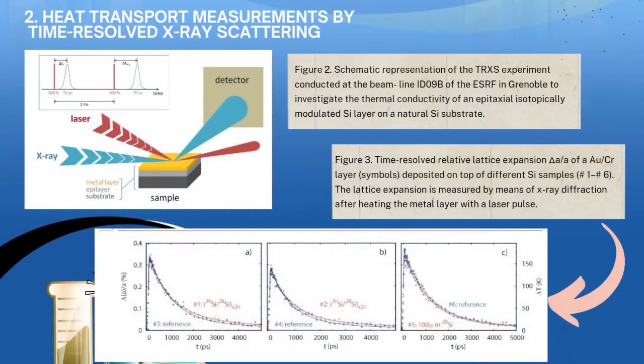Second, 2.2 heat transport measurements by time-resolved X-ray scattering. The thermal conductivity of the isotopically enriched epitaxial layers of samples 1, 2, and 5 is deduced from the cooling kinetics of the top metal layer in air after pulsed laser heating. This cooling behavior is affected by the thermal interface resistance and the thermal conductivity of the underlying material. The reference samples 3, 4, and 6 serve to determine the thermal interface resistance from the cooling behavior of the metal layer, since the thermal conductivity of natural silicon is well known.